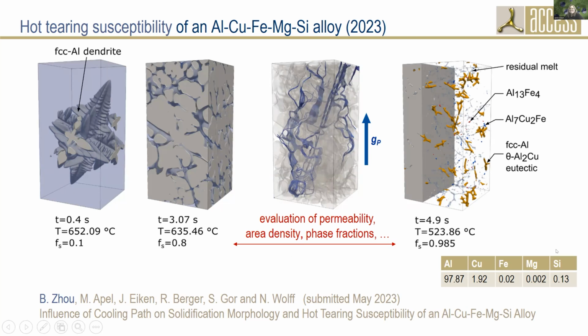So here we did not have to assess any data. The database for aluminum was quite good, and all these elements were already included, so one could start directly. Also, the primary phase is a simple FCC phase, and for this aluminum phase the anisotropy is quite well defined. So one could directly start with a simulation without doing further assessment.